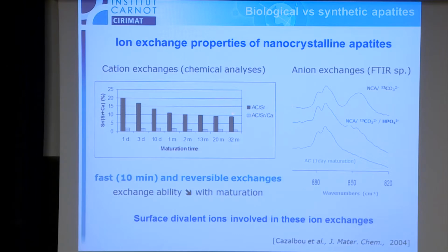Firstly, we put the apatite in a strontium solution, and here this is the ratio strontium on strontium plus calcium, which gives you an idea of the ability of this apatite to exchange strontium with calcium. You can see that the amount of strontium that can be incorporated in the apatite is decreasing with maturation.